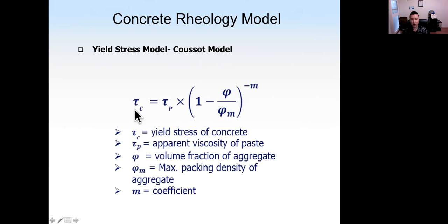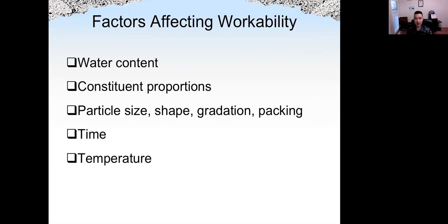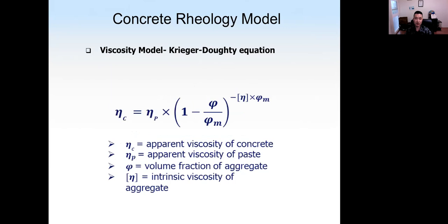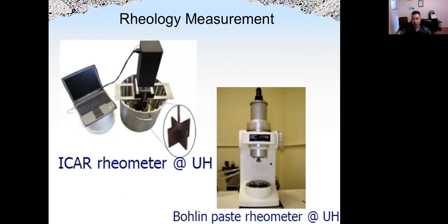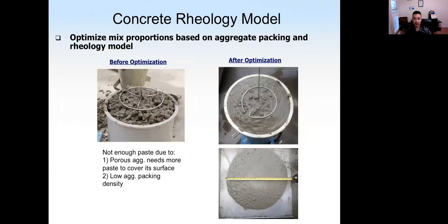This is another model for yield stress of concrete. This is yield stress of concrete as a function of yield stress of cement paste. Okay, and also the volume fraction of aggregate as well as the maximum packing density of aggregate and also a certain type of coefficient. So using that equation, we can predict concrete yield stress based on yield stress of cement paste and aggregate. So together with the modeling and also the measurement of concrete as well as cement paste rheology, we can better design the concrete. Okay.